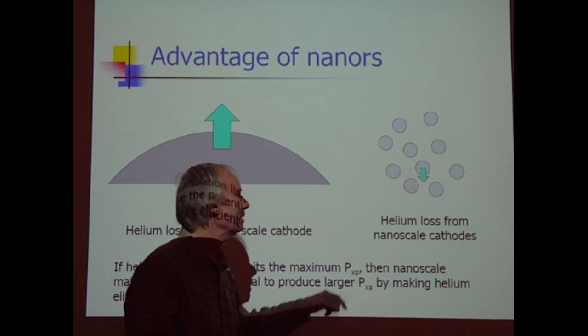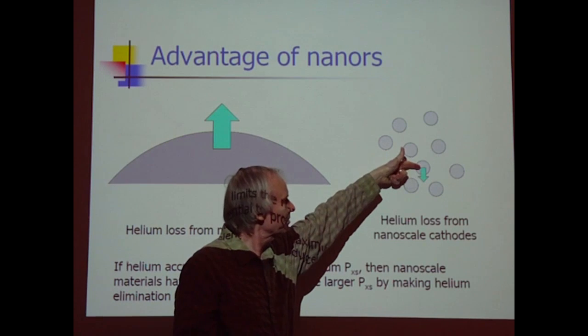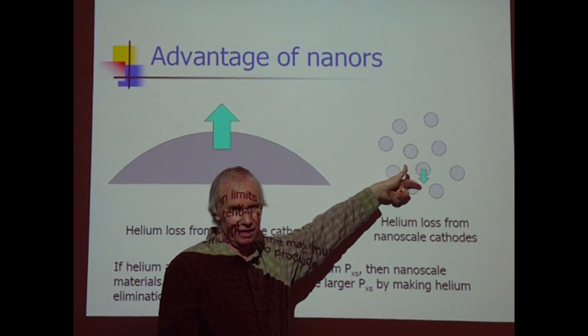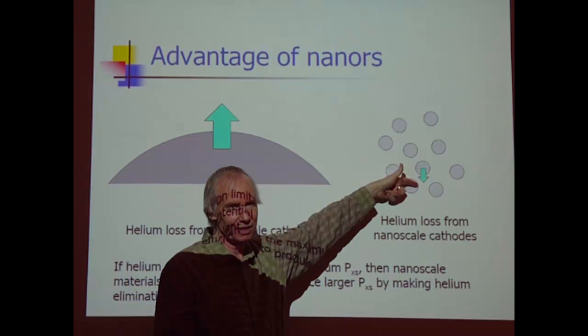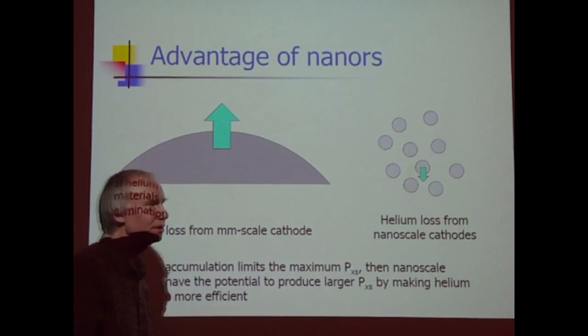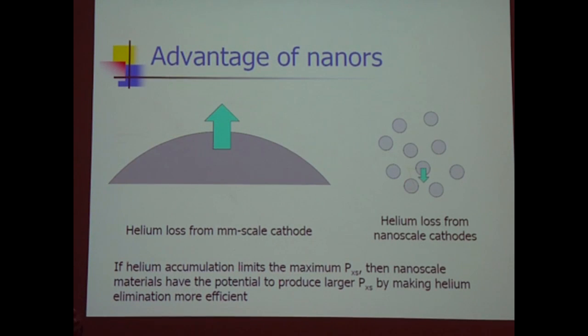In terms of how you get the helium out, we've talked about diffusion from the metal to someplace else, but you still have to get it either going through or diffusing through to someplace else. So if the matrix itself is an imperfect matrix, if it's got crevices where you can have just helium flow out, that's incredibly efficient. Helium basically passes through almost anything pretty reasonably quickly. The headache is if you've got deep traps. If you've got a lot of electrons around and you've got deep traps, then it's hard for it to move. On the other hand, if you've got an insulator, so you don't have a lot of electron density around, and you don't have a lot of embedding energy, it has the potential to move much more quickly.